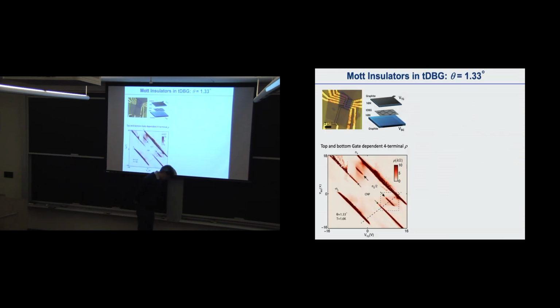So this is the kind of data we get. This is the device scheme, with top and bottom gates which control the gate voltages. Along this diagonal line, we change the density, the filling of the band. Then with different polarity, we can tune the electric field. Along this line, we tune the density, and with different polarity we can change the displacement field.